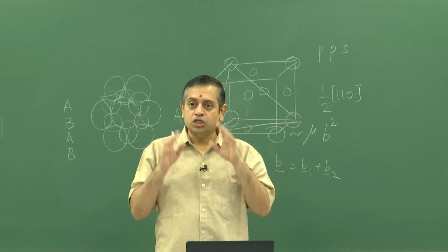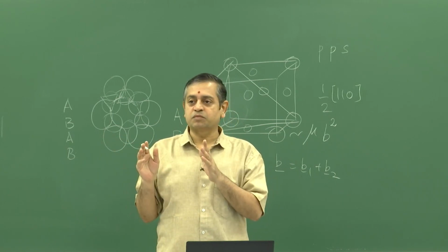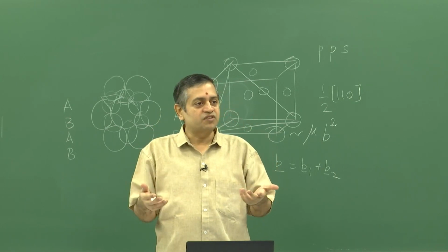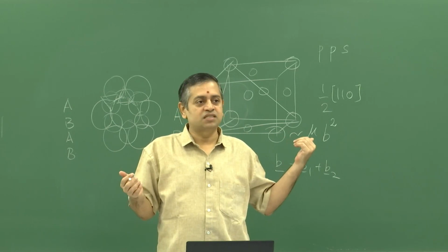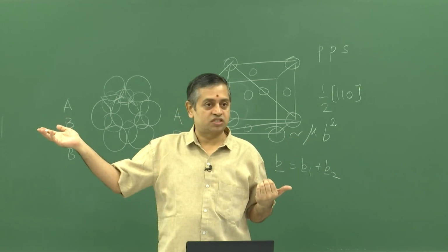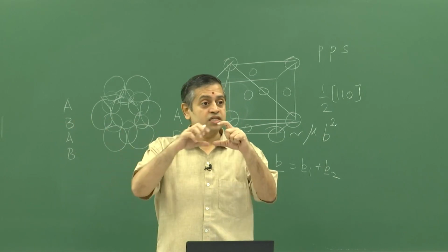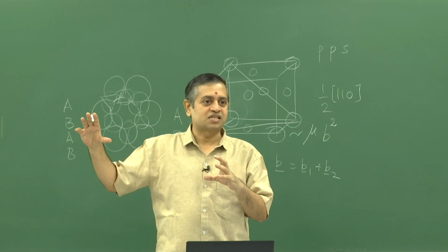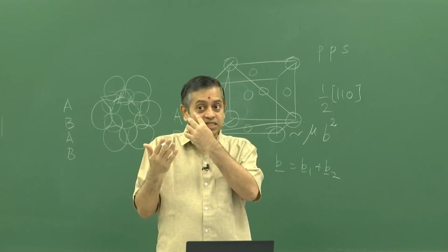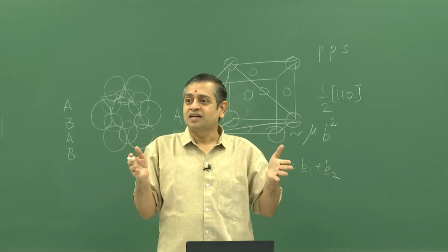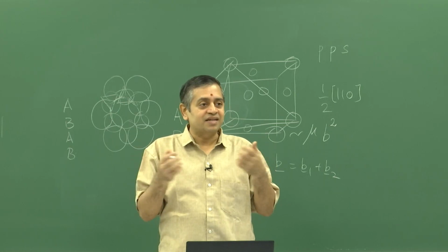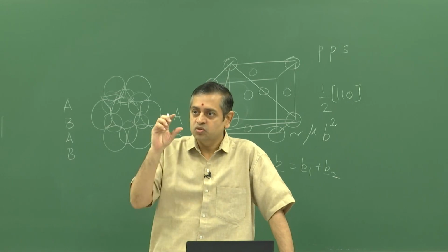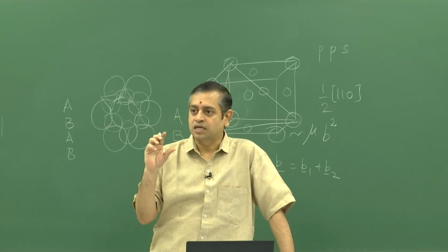Okay. So you should remember statistics becomes key, and you should always think, okay, I am doing this, is this sufficient? I said 3 simulations, maybe in this case even 3 is not sufficient. Okay. And we have also seen a methodical increase in error bars with increasing aluminum concentration, which basically tells you that your system size is small, and these local configurations can sometimes skew your results. So you need to do many more simulations to keep the error bar under control.